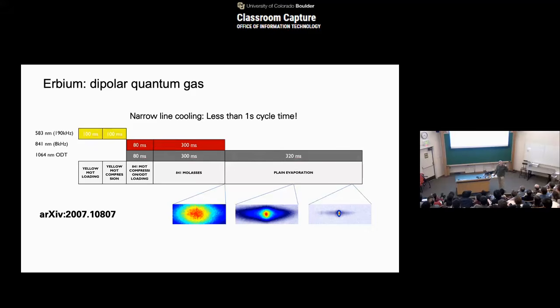And one of the nice things they got to work is that we can have a high repetition rate. And I can tell you, my other two experimental teams are so envious now, because it makes a huge difference if a measurement takes a week or a day, or a day or 20 minutes or 10 minutes, right? So in erbium, you can optically cool it very close to BEC, and then within a total of 600 milliseconds from start to finish, we can make a BEC from scratch. So now we finally can do experiments where the preparation of the cold atoms takes less time than we then use to do the many-body physics.